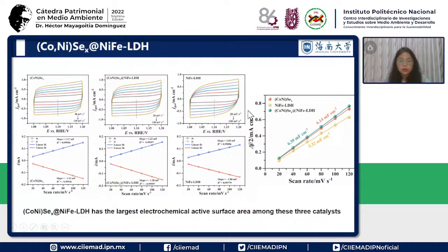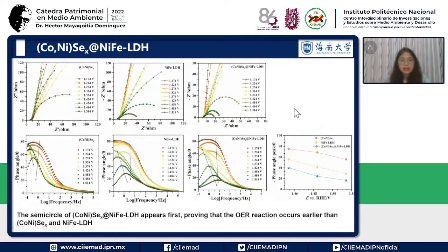And then we continued testing. We want to know about the electrochemical active surface area of these three samples. After the calculation, we found this composite shows the largest surface area among these three samples. And then we continued to get more information about the activity, and we find this composite's semicircle in the impedance appears the smallest.